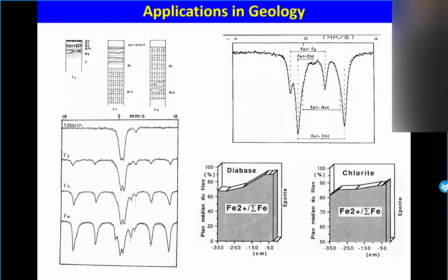Nevertheless, it was very interesting because all spectra for one zone were exactly similar. And of course, they were different from one zone to another zone. That means that his sampling was perfect. And it was after possible to distinguish the different components. So now you have such a spectrum, which is very strange. Whoa. Sextet, doublet, I do not know. But maybe there are some nano grains.